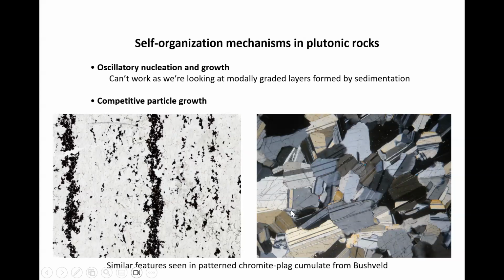And we see exactly those microstructural characteristics that we saw in the Stillwater examples, where we've got very low aspect ratio plagioclase, and we've got little pseudomorphs of the texture equilibrated melt field porosity. So again, very, very slow cooling, melt solid textural equilibration, giving us a high permeability. And critically also, we have a very, very simple mineralogy. We've just got 2 phases essentially, or 3 at most, in these rocks. So those are the key indicators for self-organization, interscale layering formation by competitive particle growth.